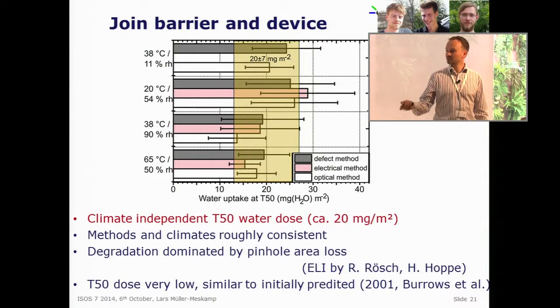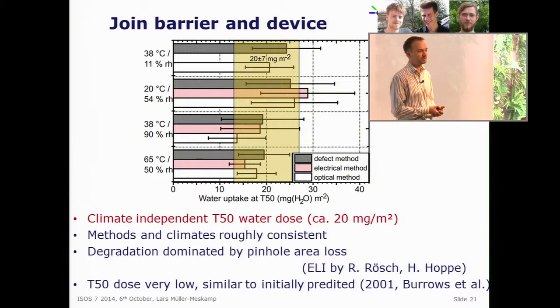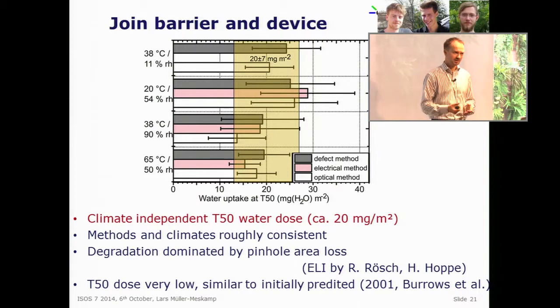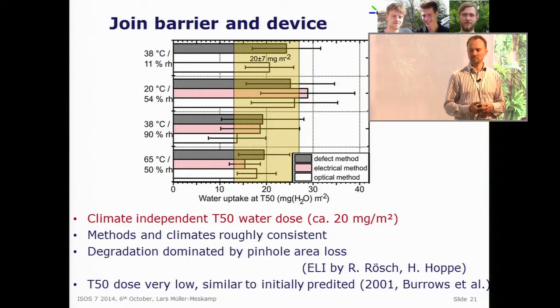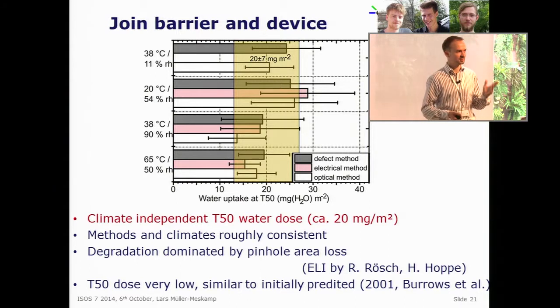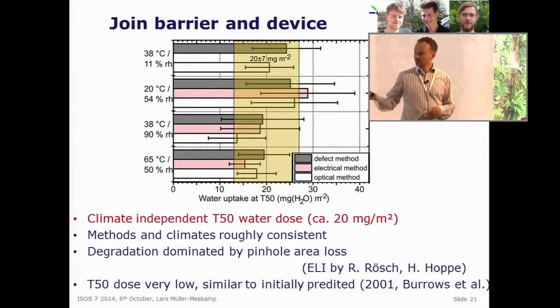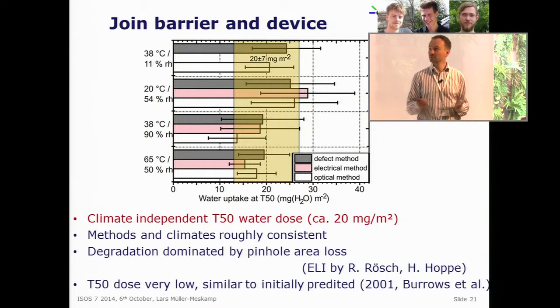And what's remarkable is basically that this T50 dose is very similar to what was predicted a long time ago in this paper in 2001 for OLEDs, where they assume that you have 5 nanometer of magnesium which corrode away. And I think they predict 64 milligrams for the whole layer. So this is not a lot, and it's probably just an interface or something very small which is dominant for this type of degradation. So probably it's magnesium.